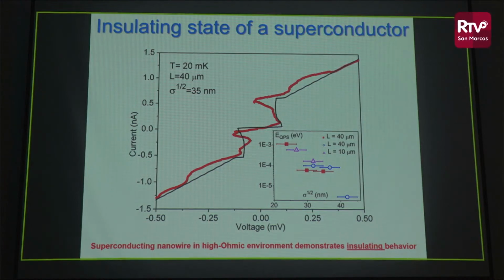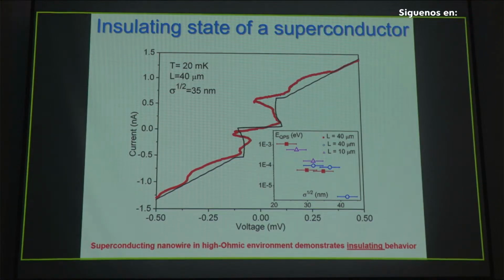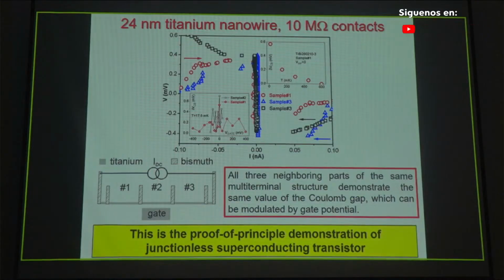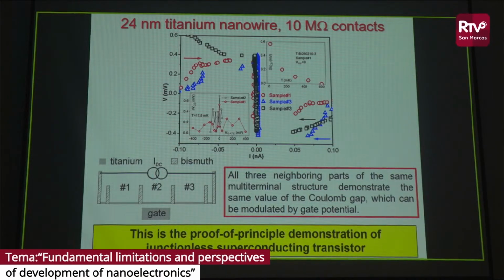Black is theory, red is experiment. It's really weird. It's a superconducting nanowire which demonstrates insulating behavior. Before you apply significant voltage there is no current going through such a superconductor. And this is the result of these quantum fluctuations. Then we fabricated a multi-terminal device consisting of several sections, 1, 2, 3, and all of them show the same behavior. The width of this Coulomb blockade is controlled by application of an external electric potential, the left inset, and the whole system doesn't work above the TC of superconducting titanium. So it's really a true manifestation of quantum fluctuations in a superconducting structure.